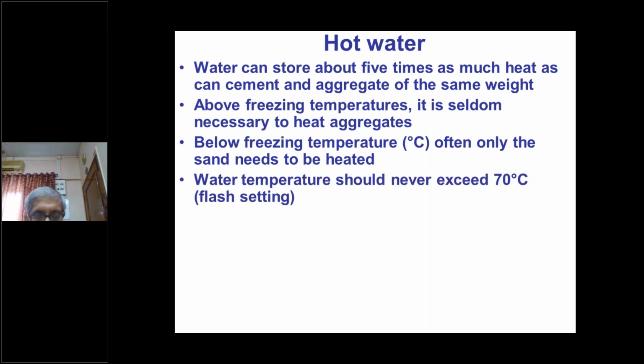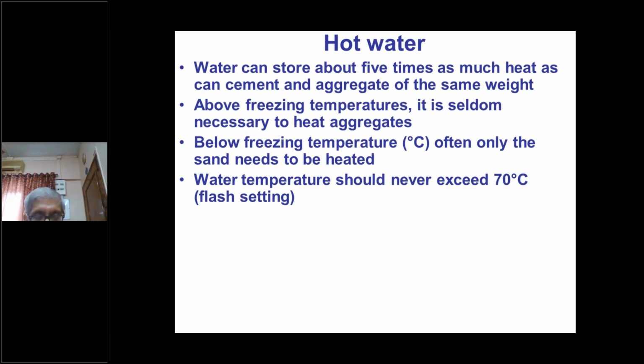Water temperature should never exceed 70 degrees. We were lucky that in Tashkent at the batching plant itself, we were getting cold water supply, which was of course in winter at 0 degrees, and hot water supply, which was in winter at 60 degrees. So we could mix the hot and cold water and get a mix of 30 degrees when we did that concreting at nearly 0 degrees centigrade.